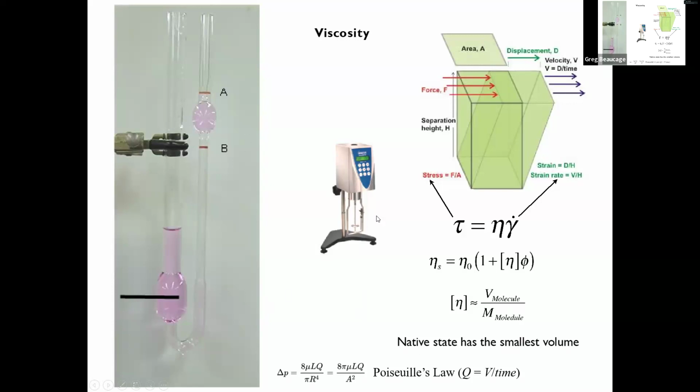This one's a little bit better. It's like a laminar flow. It's got kind of a constant viscosity across the gap, more or less. Aside from the curvature, because the perimeter of that cylinder gets larger, so the shear rate actually changes in the Couette viscometer, but it's better than the Poiseuille one. So in some sense, this is a better way to measure it. But this is a simple way. You don't need any machine. You just have this glassware.